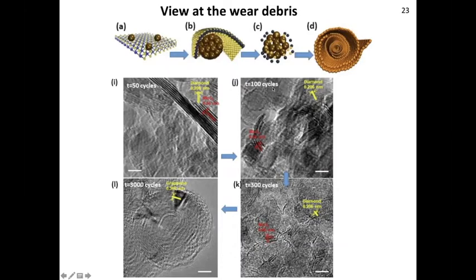When we continue sliding and stop the test at 100 cycles, the nature of the wear track is changing. We still see some MoS2 flakes, but they start to show curvature. They're thinning. Here we have up to 10 flakes combined together; here we have only 3-4 at different places. They're also rupturing, so we don't see as long flakes anymore. And they are starting to surround the diamond curvature.